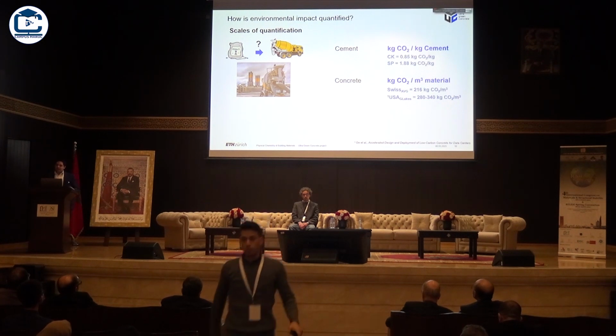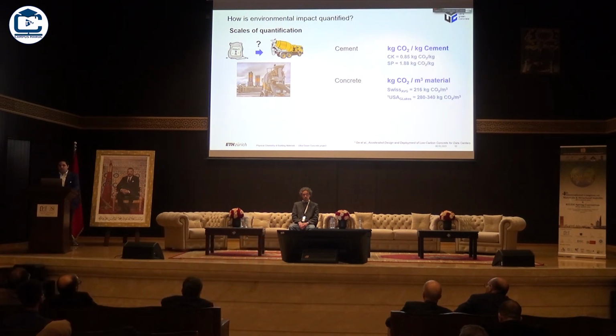A more useful scale then would be to look at the kilograms of CO2 per cubic meter of material, looking at the concrete scale. And what we see here, which is also something that Karen already introduced in her presentation, is that there is a lot of scattering. For example, the Swiss average in 2019 was about 216 kilograms of CO2 per cubic meter. But if we look at a publication looking at the situation in the USA, in the Great Lakes area, this value is around 280 to 340. So around the world, we are producing concrete with a very varied amount of embodied CO2, and this is certainly a huge opportunity for optimization.